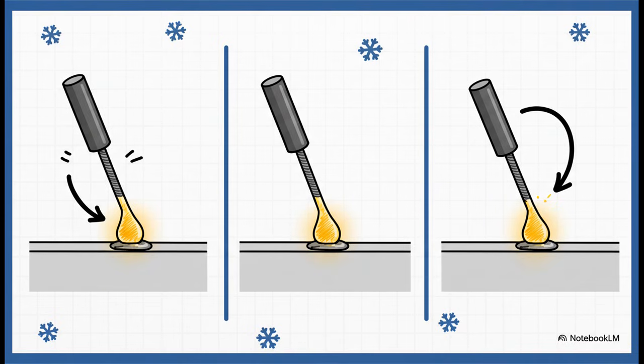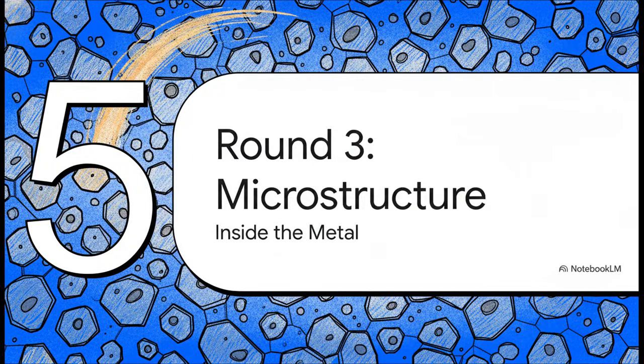Well, that's where some really clever innovations come in, like cold metal transfer, or CMT. It's basically a modified MIG process where the machine physically pulls the wire backwards for a split second with every single drop of metal. This simple action dramatically lowers the heat input. It's a total game changer, letting you use a MIG-style process on super thin aluminum or even to join aluminum to steel. All right, on to our final round, and this is where we get a little nerdy.